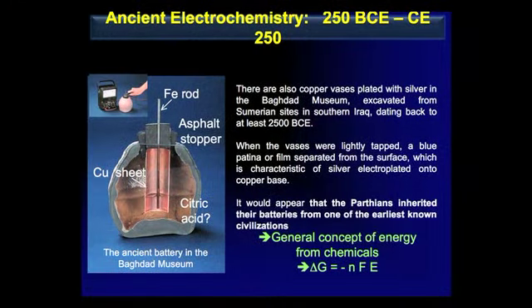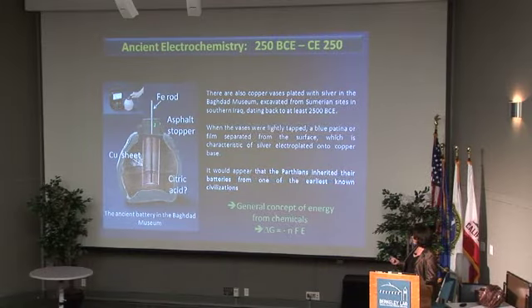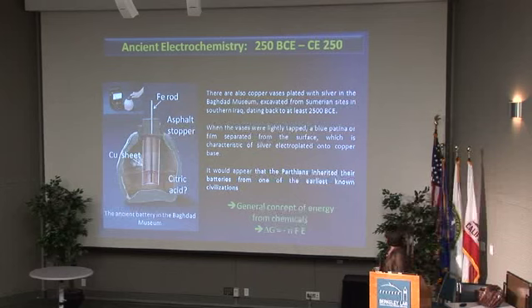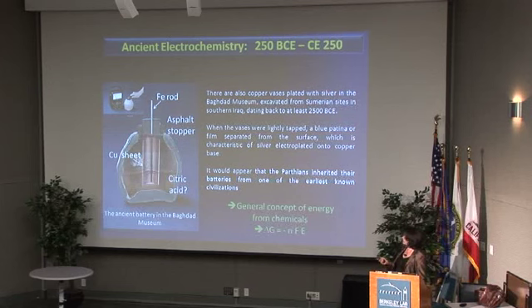So it turns out that electrochemists are, first of all, in short supply in the US, perhaps not everywhere in the world. They are also in short supply in Canada. But it's a well-worn technique. Some people think that Volta was responsible, but it appears that, in fact, it was developed a long time ago. So these devices, which are quaintly called the Baghdad battery, have been unearthed. They exist in the Baghdad Museum, and they are excavated from Sumerian sites dating back to 2500 BCE. And it's effectively just a good old electrochemical couple: there's an iron rod that sits in the center, copper sheet on the outside, and it is thought that the electrolyte was something like citric acid or vinegar or other acidic solutions. And when these things are coupled up, they actually produce a current.